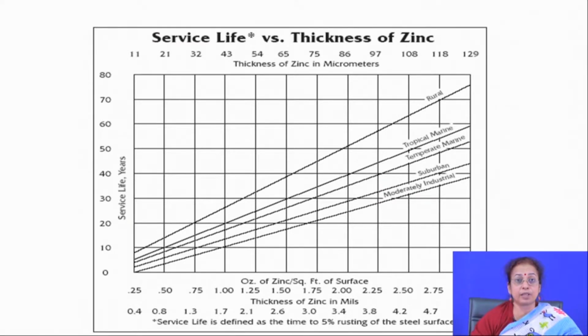Spray deposition technique also offers very high thickness, but the interface is not as strong as in hot dipping, and there are a few porosities or defects on the surface. So, it is usually observed that hot dipping is preferred to the spraying process for zinc deposition, where you are looking for a very large service life of the component.